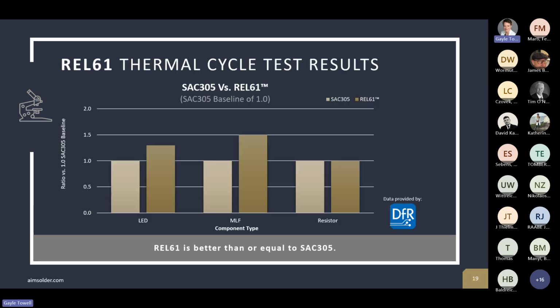This is the result of some thermal cycle testing. We have REL61 compared to SAC305, treating SAC305 as the baseline, and we looked at the performance across 3 different component types. And we see that while the performance was pretty similar for the resistor component, REL61 had superior performance across the LED component and the MLF component type. So with thermal cycle testing, we had, again, REL61 performs better than or equal to SAC305, depending upon the component.